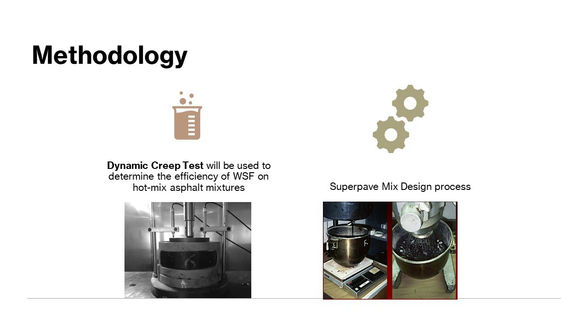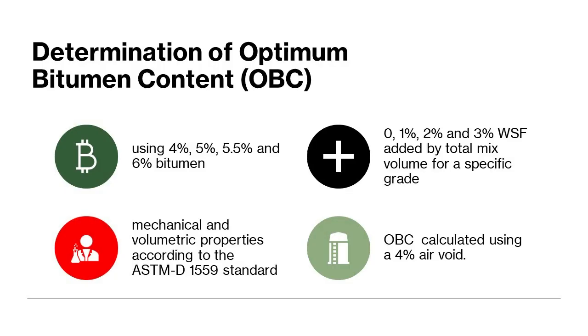Each sample of 100 and 200 grams of asphalt mixture is used for the study. The asphalt binder is then applied until the desired density is achieved. Before adding the steel fibers, the mixture will be blended manually and with mechanical blending according to the percentage of asphalt, which is 0, 1%, 2% and 3%. This study will prepare 16 samples using 4%, 5%, 5.5% and 6% bitumen with 0, 1, 2 and 3% waste steel fiber added by total mixed volume for specific grades.